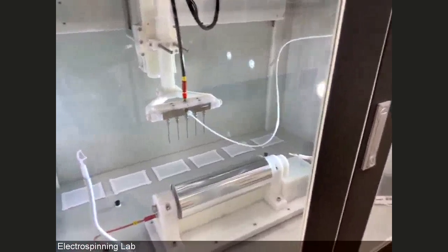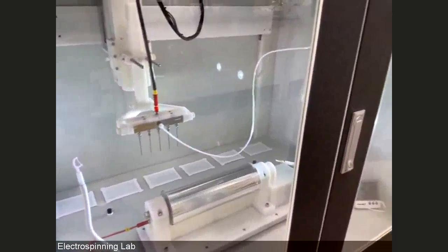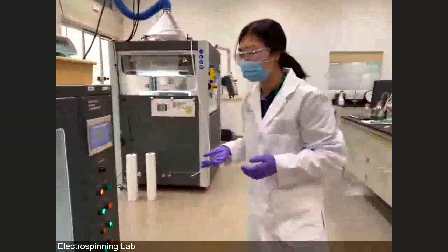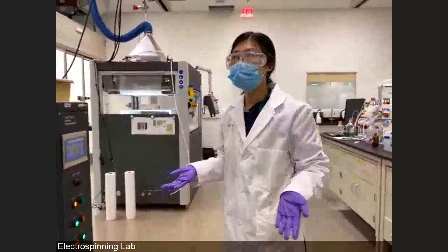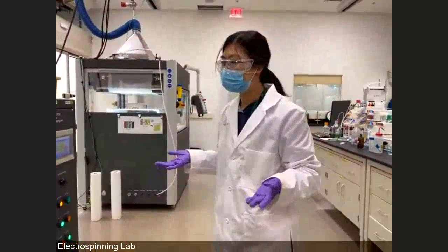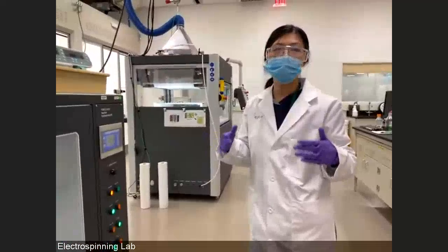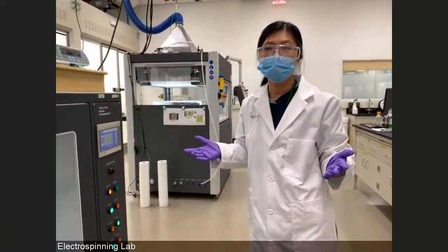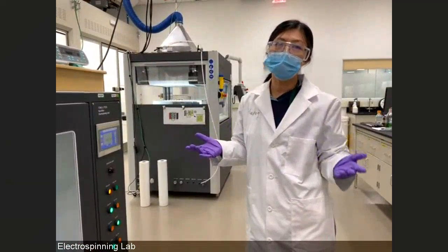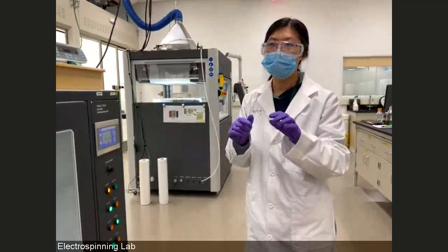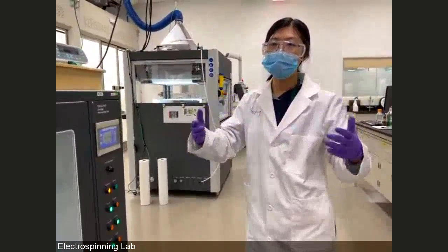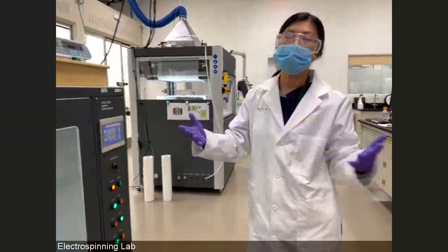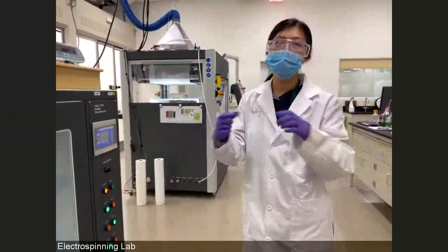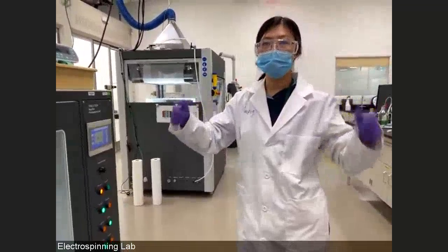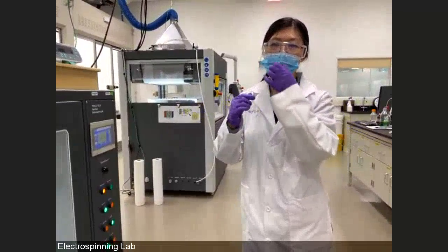So as you can see, the electrospinning setup is a simple process. However, to scale it up, it actually introduces a whole lot of complexity. There are two ways that you can scale up electrospinning. The main goal is to introduce as many electrospinning events as possible. One way is to use needleless electrospinning, where you have an electrode and you introduce the solution to the surface of your electrode, and the electrode can be a metal wire, a rotating drum, or a ball, so that it has a large area.